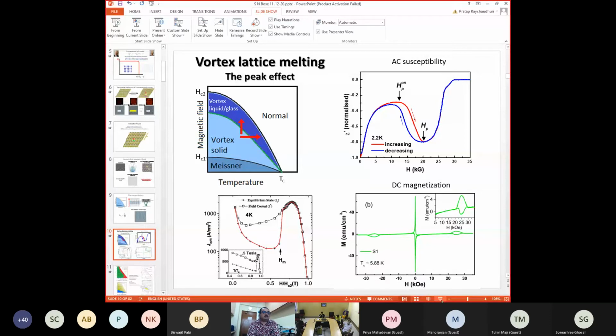Now this melting transition gives its signature in various properties. For example, if you measure the critical current of the superconductor, you will see that at this melting transition, you have a sudden anomalous increase in the critical current. So this is as a function of magnetic field, and I am going in this direction. I am increasing the magnetic field at a fixed temperature. And this is the data by Henderson et al. And you see that this critical current normally you would have expected to reduce continuously to zero here. But instead it shows this large anomalous increase here, and it shows this peak before crashing to zero. So this increase is a signature of this order-disorder transition.